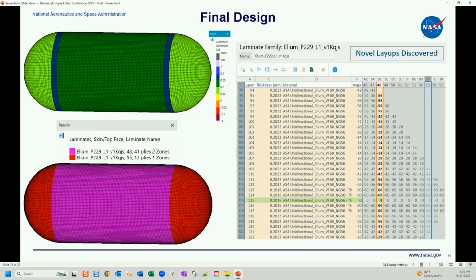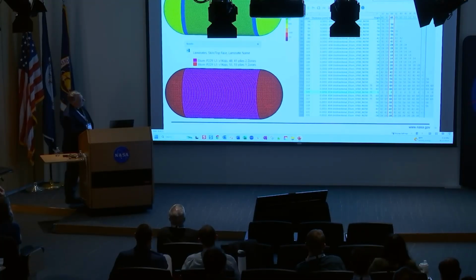So at the end of it, I just went in and opened the database, and this is what it was showing. So here are the minimum margins of safety. You can see they're all positive, and it actually didn't really need the transition zone. I can't really tell which zone the transition went with, but you see the barrel is 41 plies. You'd expect that to be right. That's the higher stress region of a cylinder, and the domes are 13 plies. And you can see here's the laminate family, the material, and I tried to highlight the two laminates there so you can see the stacking sequence with the middle thinner ply pack there.